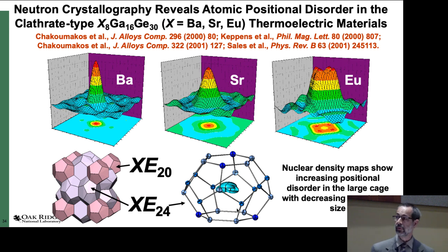You can see the positional disorder in the large cage of these clathrate compounds in the Fourier maps or maximum entropy maps. The split site models for strontium and europium actually improve the structural refinements.